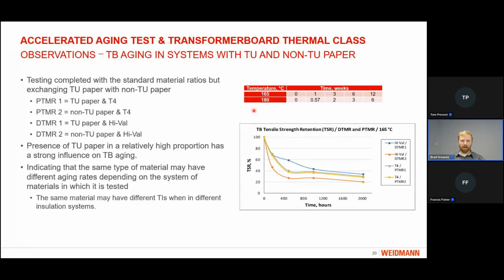For this smaller test series, we did a reduced aging period of the 180 and the 165 for various temperatures, but really trying to build the same aging curves that we saw previously. So what we learned from this is we can look at the aging curves here. If we look specifically at the high val and paper curves, so high val and TU paper is this blue curve here, and high val and the non-TU paper being this orange curve here, we see a significant difference in the aging rates and aging curves of those two ratios, with the only difference being the thermal upgrading, the presence of the thermal upgrading agent.